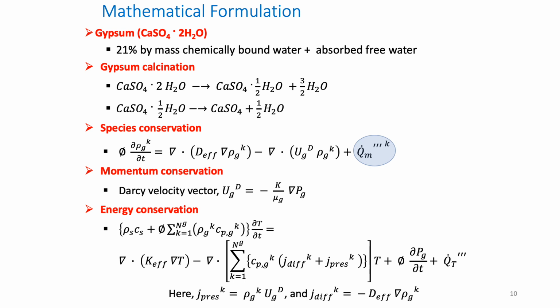The most difficult part of this is the source term in the species conservation equations for water vapor, as gypsum calcinates, the chemically bound water gets released as water vapor. So this needs to be accurately predicted in order to model gypsum calcination. And we need to have gypsum thermochemistry models to model the source term in the species conservation equation.